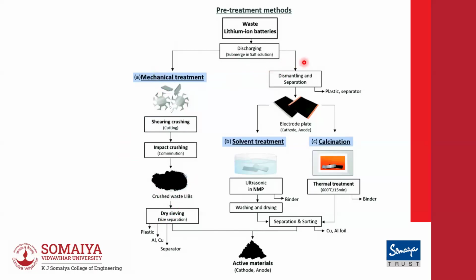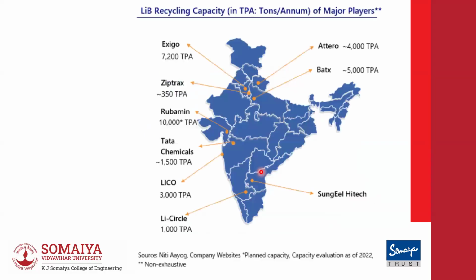I have another option where I can take the foils themselves, the aluminum and the copper foil, and then I can separate the materials. I can do a calcination by means of which I dry off the material and then sort of scrape it and separate the foil. Or I can dissolve the material in a solvent, and then the solvent is retreated to extract back the material. So in this case, I'll be dissolving the foil also sometimes.